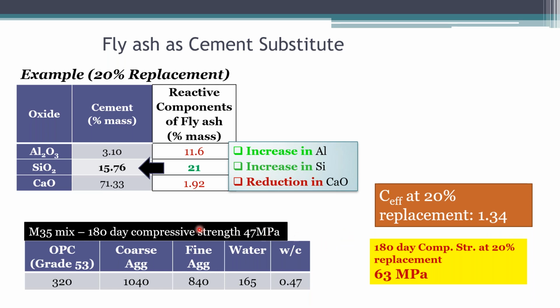And we developed an M35 mix, which gave us a compressive strength of 47 megapascal using normal OPC 53 grade cement. But when we did a 20% replacement, because it had an efficiency factor of 1.34, we were starting to get much higher strength of 63 megapascal. But of course, we had to wait much longer because fly ash is a lower reacting material. And so I cannot expect this to come up at 28 days. So one of the things that we have to look at, if we are going to look at clinker substitution, is also to relax the requirement of 28-day strength.